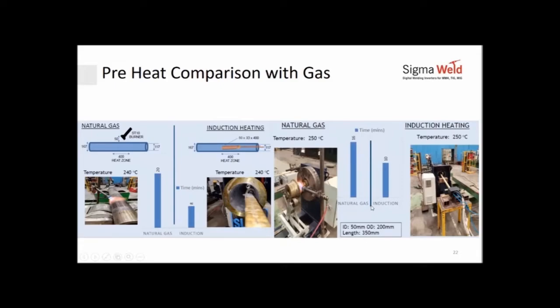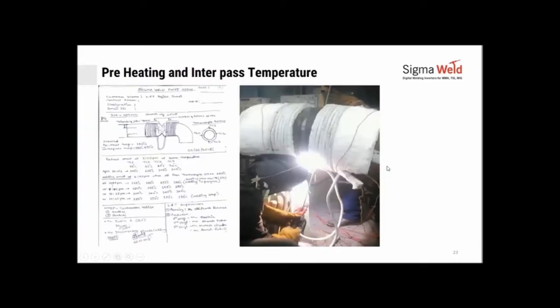Again, if you look at the OD, here is a very heavy, thick component being preheated. So again, with gas, it took about 16 minutes to bring in the temperatures on the surface. No way to measure it on the inside. However, here, since the heating is happening from inside, when you measure on the surface, it's ensured that the heating inside is equivalent or above the temperature. Again, assured much lesser time, much better accuracy of heating.